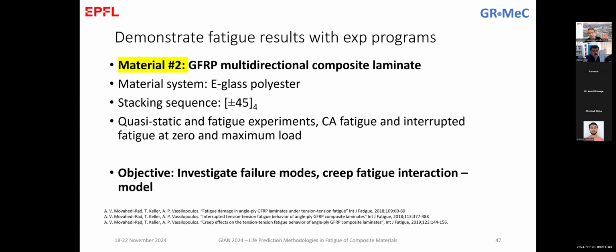And in this previous experimental program, we did only one stress level, and we tried to correlate the interrupted fatigue results to the continuous fatigue results. Here we repeated this for a complete SN curve with a different material, and we added the interruptions at maximum load. Again, discussing the experiment and why we did these tests and not others.